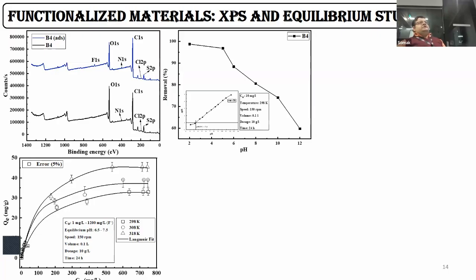So in case of negative surface charges, the surface of the bead starts repelling, and by this repulsion, the removal of fluoride is not that effective. But when the pH is lesser than the isoelectric point, the surface of the bead being positive, it starts attracting the fluoride and it gets imbibed within the hollow pore structures present inside the beads.